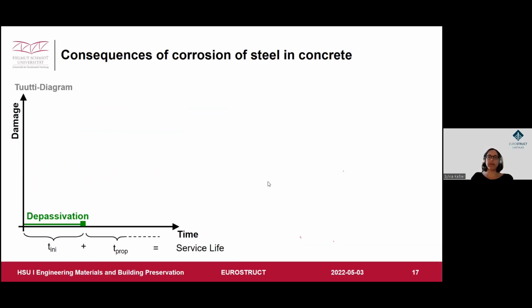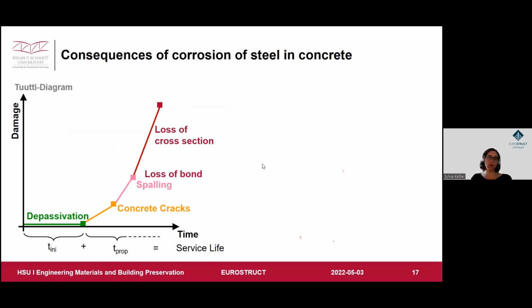So next step, I come back now to the Tuutti diagram. Now the next step, as soon as we have corrosion going on and iron products, iron oxides are produced, they need a much higher volume, which leads to stresses in the concrete. As soon as all the pores in the concrete are filled with iron oxides, and the more iron oxide is produced, very easily the tensile strength of the concrete is exceeded, which leads to the concrete cracking, and afterwards to the concrete spalling, to the loss of bond, and to the loss of the cross section.